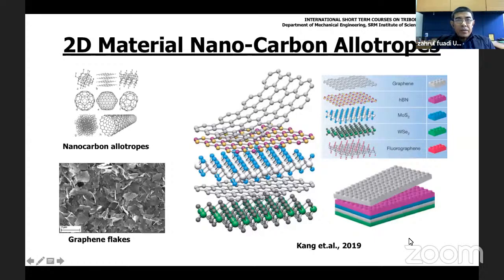And the third one, we can also produce some sort of carbon-based tribofilm on the contact interface using 2D materials. We have many kinds of 2D materials here, for example graphene, hBN, MoS2, WSe2, or fluorographene. So this carbon structure is two-dimensional. For example, here we see these graphene flakes, and these graphene flakes can be used as additive.